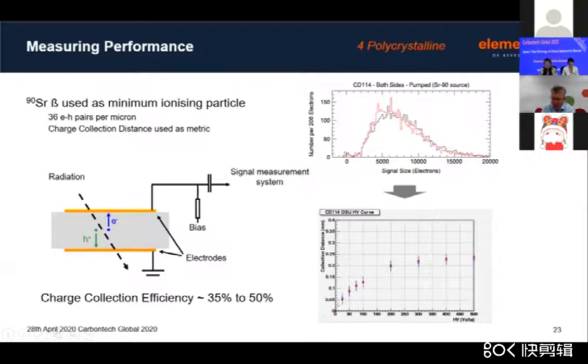And what you find in polycrystalline diamond detectors is that generally they saturate with a certain voltage, and their charge collection efficiency is limited to around 35 to 50%, i.e. the number of defects in these materials is still there, and that's what we got.